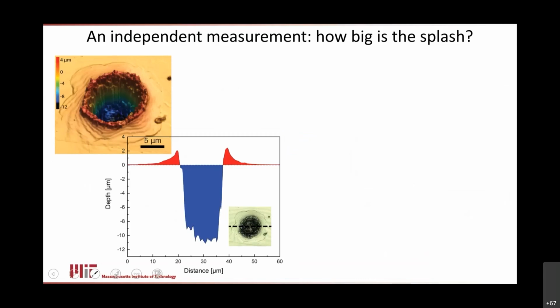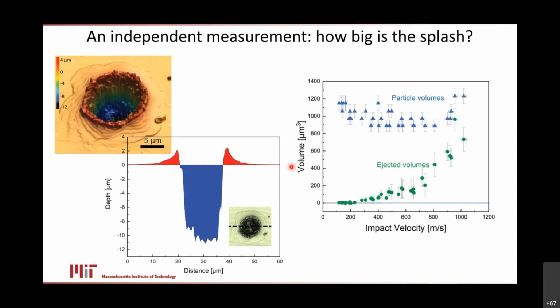But now, because we've designed this experiment so that there's no particle sticking there, the particle flew away, we have an independent way to come at the volume measurement. We can use quantitative confocal surface measurements, and we can literally measure the volume of lost matter. Because we can measure the amount of pileup, we can measure the depth of the crater. We do that fully in 3D, and the difference between red and blue here gives you the amount of lost matter. So it's a volume conservation from a flat sheet. You can calculate exactly how much matter you lost.